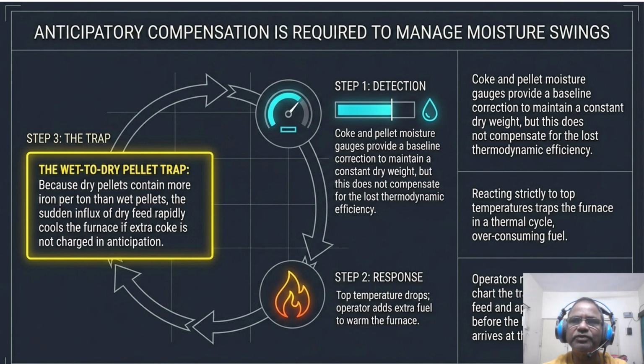But look at step 3, the trap. Because dry pellet contains more iron per ton than wet, a sudden influx of dry feed after a wet spell rapidly cools the furnace due to the increased metallic load. So if you are not charging extra coke 6 to 8 hours before the dry iron arrives at the cohesive zone, you will trigger a thermal cycle that destroys your fuel economy. You must chart the transition,